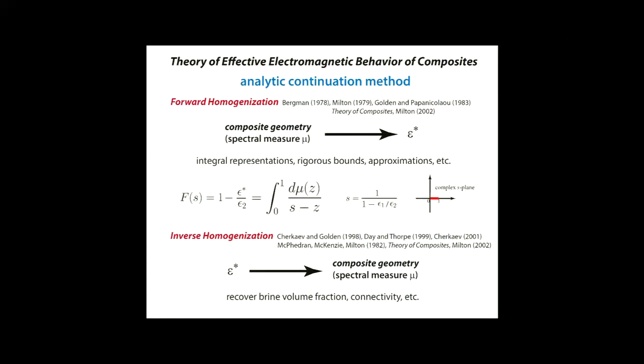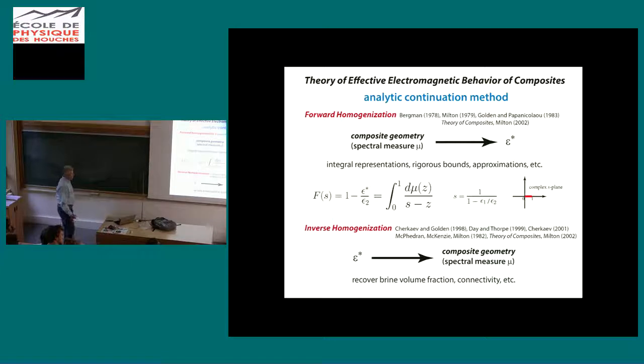And then a very powerful method that I got involved with my first year of graduate school at Caltech with George Papanicolaou was the so-called analytic continuation method. Very beautiful mathematics where all the geometry information is contained in the spectral measure of a self-adjoint operator that I'm going to mention in a second. And then you get integral representations for the effective complex permittivity. That's it right there. This function F of s is analytic off the interval [0,1] in the s plane, where s basically just involves the component parameters. And then we're also interested in inverting this whole process, where you're given bulk information about the composite and you want to invert for the spectral measure, which contains all of the geometrical information about the composite.